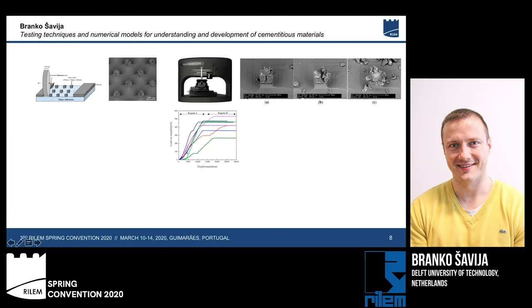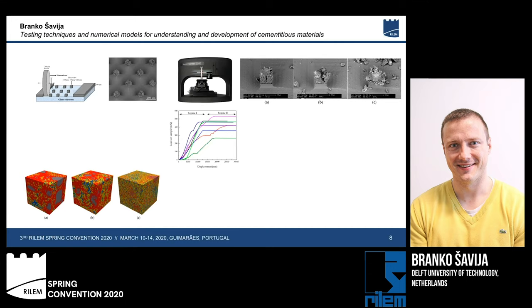Now, from this, we still have global properties of our cement paste at this very small scale, but we are still interested in properties of individual hydration phases in the material. So here we go and use our numerical simulations again. We use microstructures for our materials that we can again get from either microstructural simulations such as HYMOSTRUC, or in this case from X-ray computed tomography.